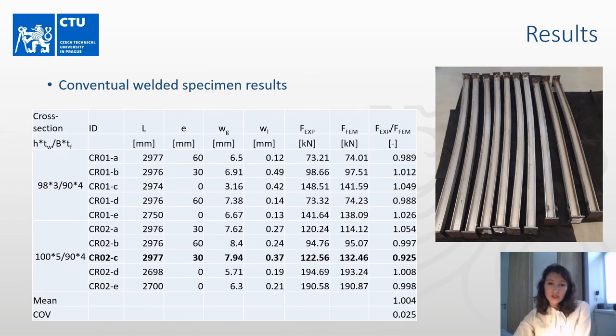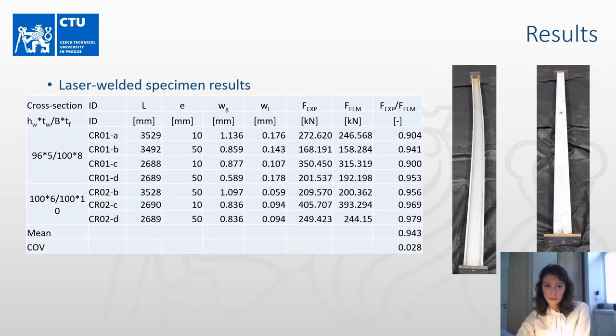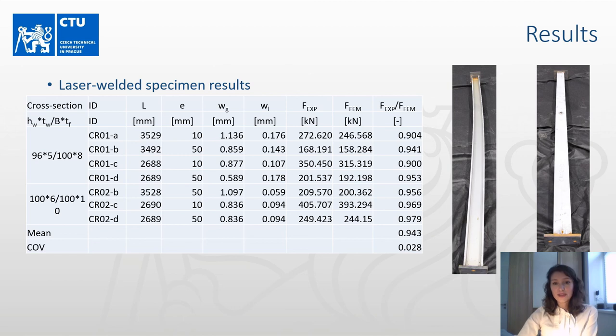The results of all conventional welded specimen tests are given in a table, and the test results were compared with the numerical model. For conventional welded specimens, the model can be considered accurate enough — the mean ultimate force to experimental force ratio is 1.004 with a coefficient of variation equal to 0.025, which is a quite accurate result. However, in the case of laser welded specimens, this ratio is 0.94, so work on validating the numerical models will continue.